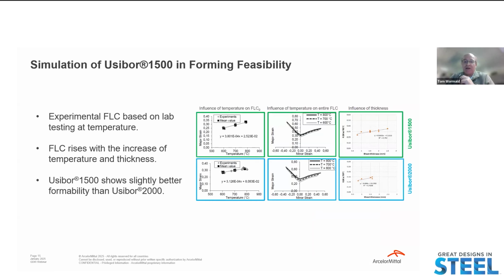With an increase in thickness and temperature, there is an improvement in the forming limit curve. It's largely up to the user to choose the preferred temperature for evaluation of the results, and that's commonly between 600 and 800 degrees Celsius.